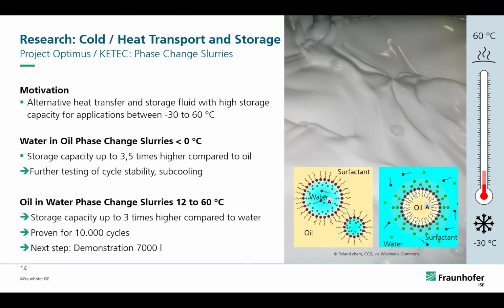But what we really investigated a lot is the oil in water phase change slurries, where we can operate in temperatures between 12 to 60 degrees. And here we have a storage capacity that is 3 times higher compared to pure water systems. We have lots of cycles proven, and we also have a demonstration in a scale of 7,000 liters in a domestic heating application plant.